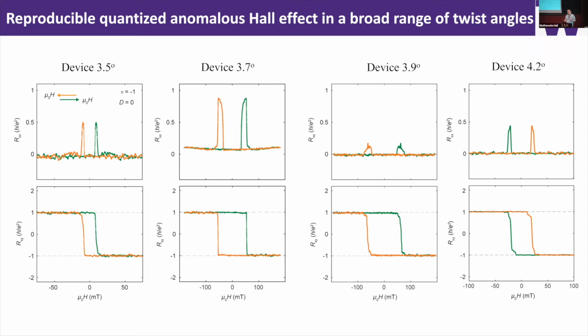One of the reasons, I think, is that the quantum anomalous Hall effect in twisted MoTe2 doesn't sensitively depend on the twist angle. From the results of the whole community, we know that this quantum anomalous Hall effect exists from twist angles around 2.1 degrees all the way to 4.2 degrees. So you can see there's a large range of twist angles for this effect. Here I show you four devices with twist angles 3.5, 3.7, 3.9, and 4.2 degrees. They more or less look similar. We have quantized Rxy at zero magnetic field with a suppressed Rxx.